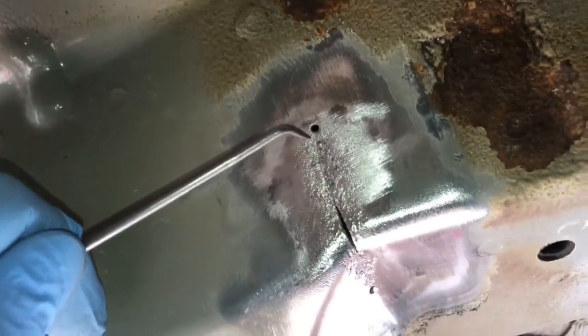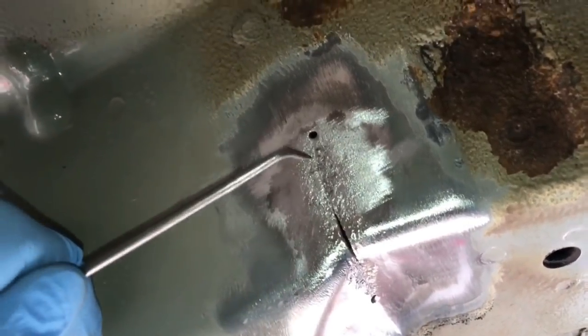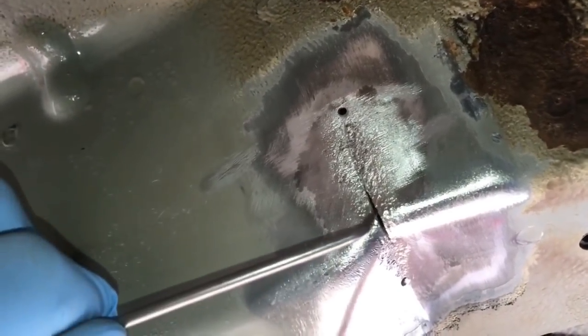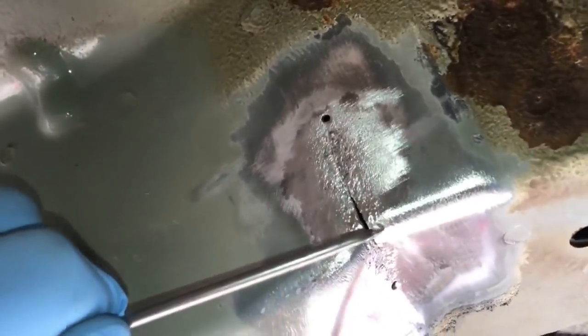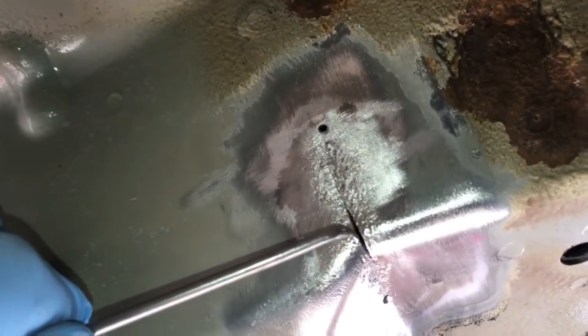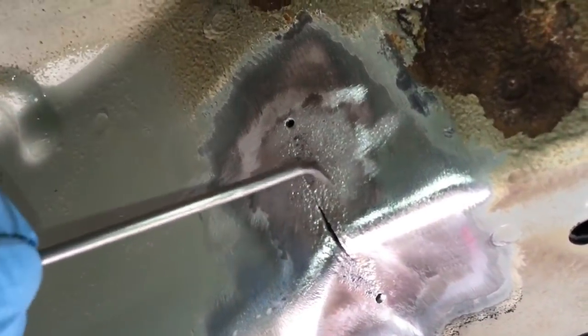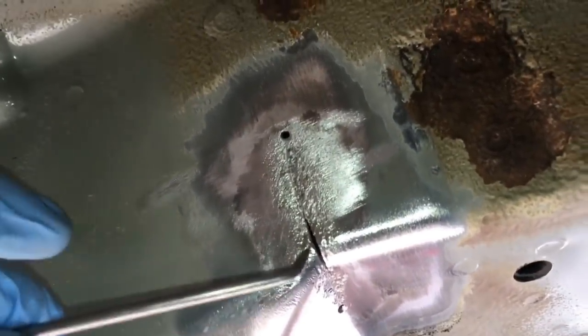And the stop drills are stopping the crack and dead-ending that, and now we can put weld through primer on there. It's likely to be very tricky to weld, not only because we've got a gap here, but also because the corrosion is not just on the surface of the metal, it's all the way through the metal, and that gap I'm pretty sure is there because corrosion has actually eaten the metal away rather than it moved under its own forces.